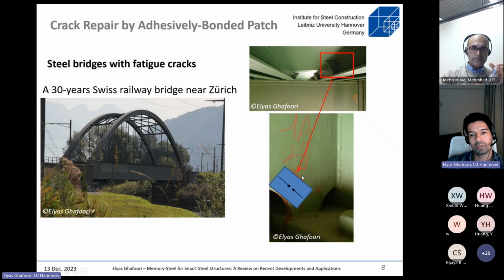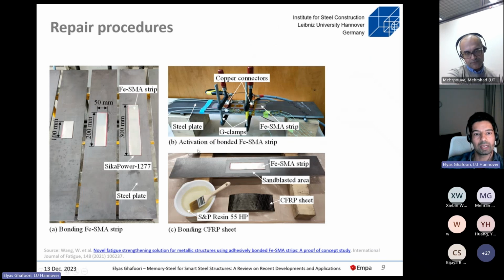Here we try to use a Fe-SMA patch that could arrest the existing crack. We bond the Fe-SMA to the existing crack detail, and then we just heat the area over the crack to activate the pre-stressing, or to pre-stress the patch, and the reaction is applied to the crack. And when the crack is under compression, the crack will not grow anymore. We know that the crack grows under tension. So this is a running project right now.